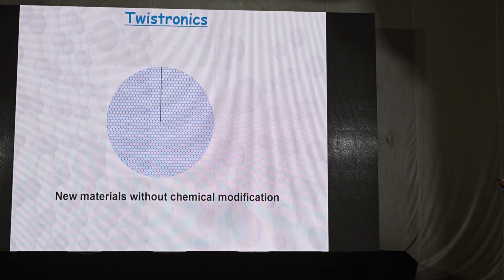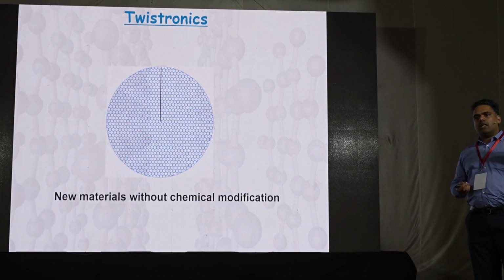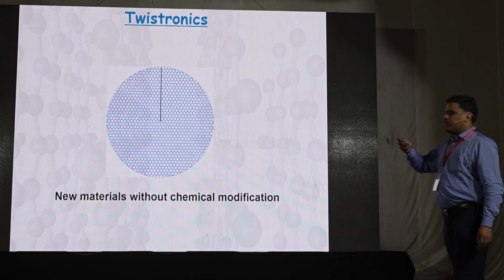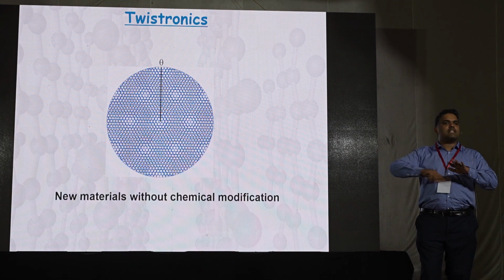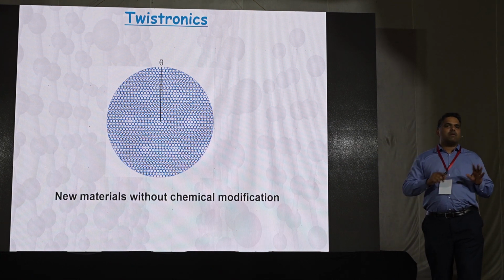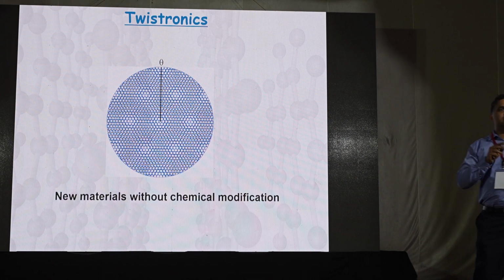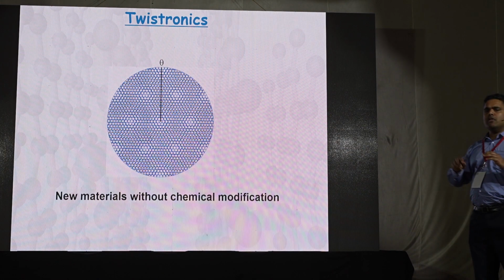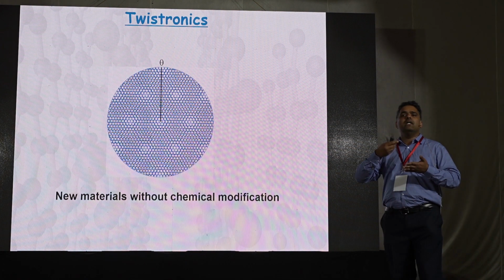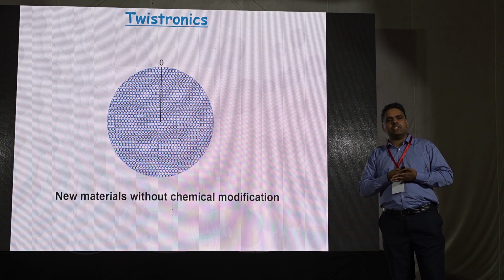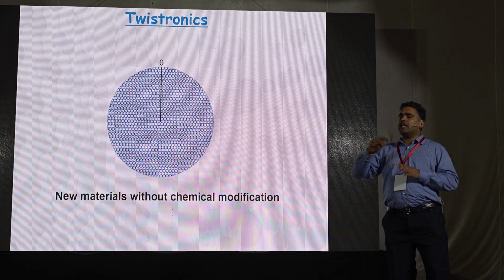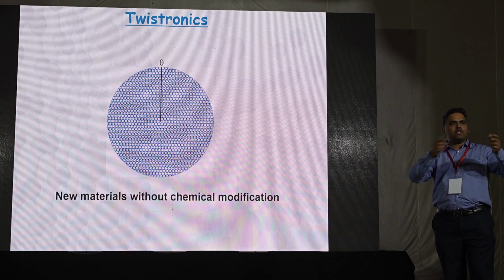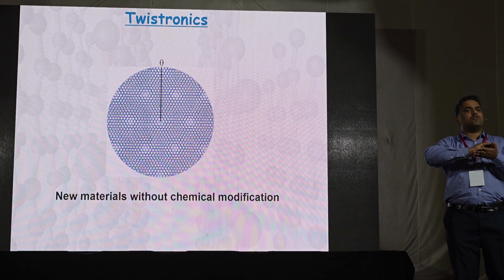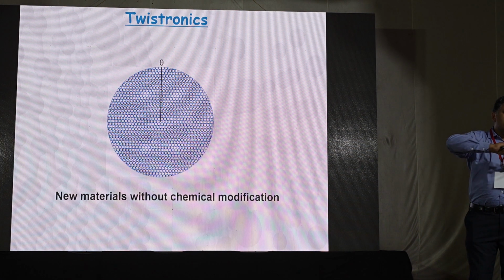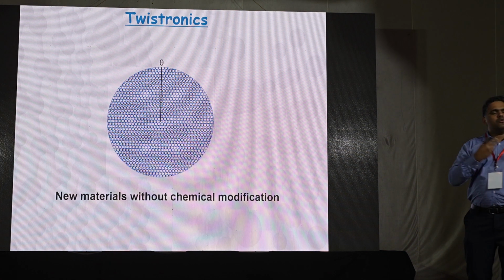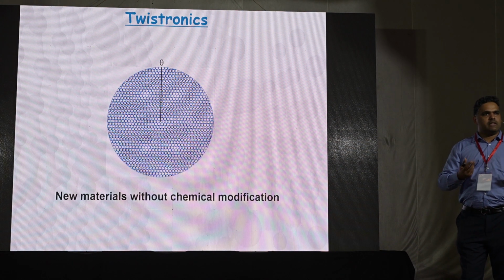Another example is, you don't need to stack many layers. You take 2 layers, like graphene and boron nitride. Put 1 layer on top of the other, and then rotate the second layer with respect to the first layer, you get a lattice. I don't know how chemists know this, but physicists, they like superlattice. When you put one material on top of another, especially if their lattice is closely matching, it creates a superlattice. Superlattice means it creates a new pattern. This, again, you can make yourself. You make 2 meshes, identical, and put 1 mesh on top of the other, and the top one you rotate. You create a new kind of pattern. The new lattice means new property, new electronic property, and everything.